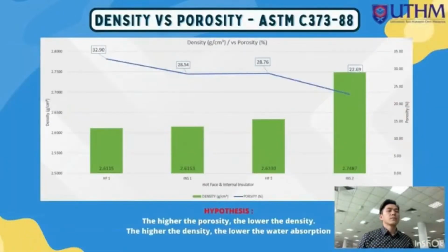As you can see from the slide, this is the density versus the porosity graph. I have conducted this experiment using the standard ASTM C373-88. So this graph shows the density value and also the porosity value, which were calculated from the formula, for the hot face insulator and the internal insulator.